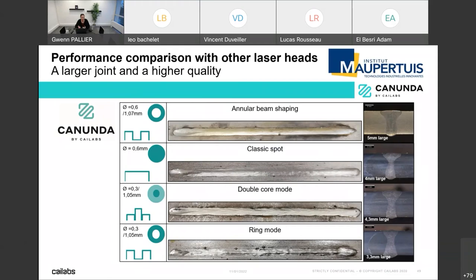So the most used technology to do beam shaping for welding is a double core fiber laser. It's a specific laser with a delivery fiber, which is made of two different cores, and you can have energy inside the main core or inside the ring core outside of it. And what was maybe not that obvious is that when you have energy only inside the ring mode of this laser, you definitely don't have the same quality compared to our systems. You have a lot of spatters. Your keyhole is actually not symmetric and way smaller. So this is what we can bring with MPLC to laser welding.